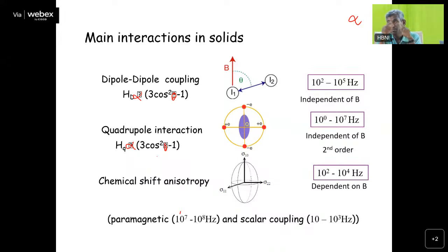Somehow, if you can make all the bond vectors at an angle theta with respect to the applied field, and then manipulate theta in such a way that cos squared theta becomes 1 by 3, then the dipole interaction can be averaged out. How we will do this averaging out, we will discuss. So that is why we are saying this dipole-dipole interaction has an angular term of 3 cos squared theta minus 1. Similarly, we also have a quadrupolar interaction.